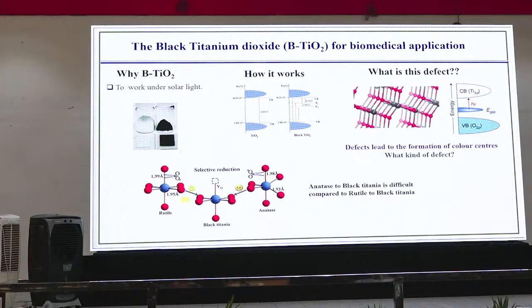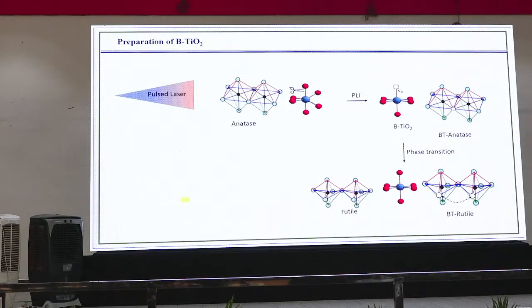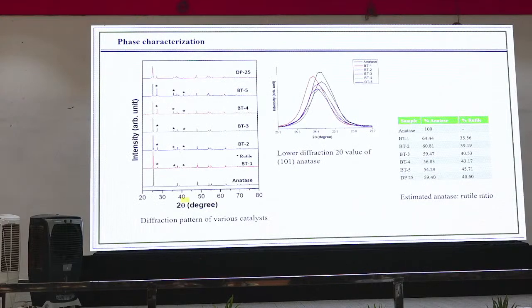But usually converting rutile to black TiO2 is easy compared to anatase. This we were able to achieve using the pulse laser. So what exactly happened when we used the pulse laser? The anatase phase has that kind of geometry, where the oxygen gets cut and creates a vacancy, and that vacancy has to get adjusted, so a few of them change phase from anatase to rutile, and it still induces the black color. When we keep on irradiating for 1 minute, 2 minutes, 3 minutes, the rutile concentration also increased and we were able to get the black color. So I believed at that time it would be a very good material for photocatalysis or electrocatalysis. We can do water splitting or something else like that, I believed.